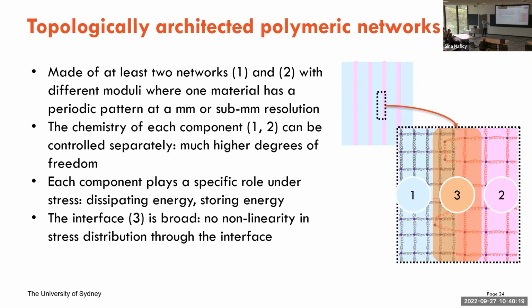The second main difference is actually the last part. The interface between these two phases is very broad. This is completely opposite to most conventional composites. So we have an interface which could cover the whole second phase, meaning that these networks are completely merged inside each other. That's the main difference that they have with conventional composites. What it means from a mechanical point of view is that if there's a stress or deformation, if you travel from one side of this to the other side, you wouldn't see any non-linearity in stress. So it very nicely distributes the stress from one phase to the other phase.